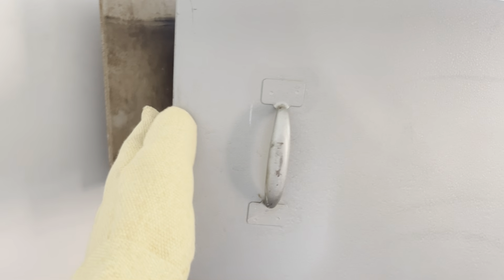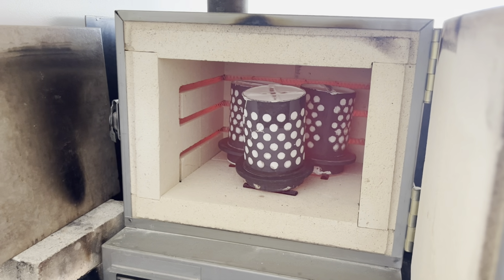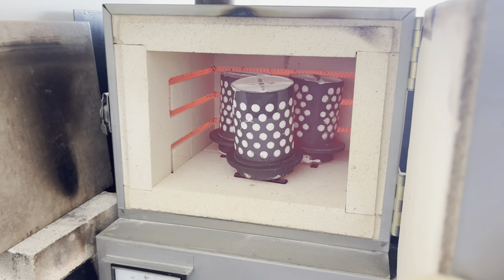It got up there, I held it for at least 3 hours minimum. The smoke stopped after about an hour or so, so I'm very confident that these are really well cooked. Something that I have noticed about this kiln though is that the temperature doesn't come down very quickly, which is fine. Basically, I guess it wants to stay hot, which is good. That's what a kiln's designed to do.